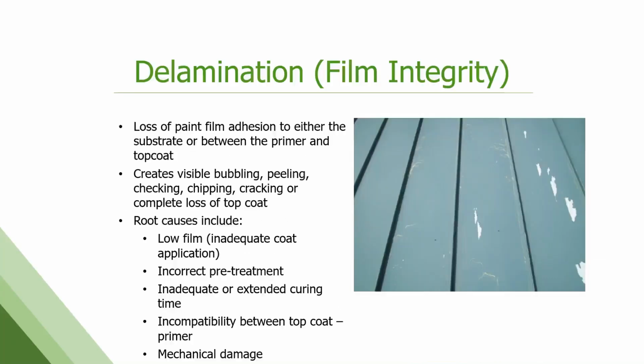And the last one is film integrity or delamination. This one we do see, it's a tough one to determine root cause. This can be either the top coat coming off and away from the primer, or the entire paint system coming off the metal substrate for some reason. It's usually a bubbling or peeling. Sometimes you get little chips and cracks that show up. And again, a lot of reasons for this, but the most common would be low film.